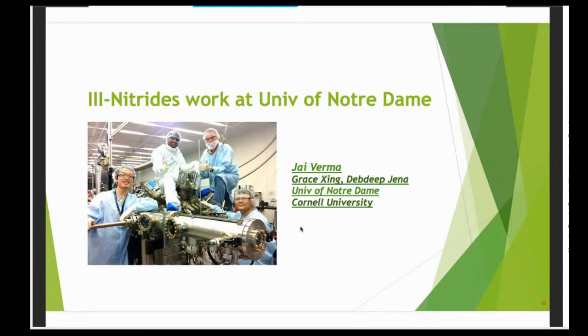But what you see is a machine and some people fooling around with it. But that's not the case. We are actually sitting on $1 million equipment over there. So this equipment was used to create layer by layer deposition of the III-nitrides, gallium nitride or aluminum nitride or indium nitride material, and grow crystals out of it. Generally, with silicon and all, you grow crystals in the form of a boule, like you just lift out, like you deposit sugar crystals or so.